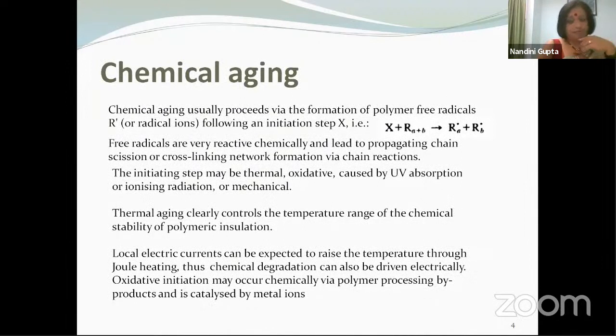Sometimes it can lead to a good thing. For example, if you prepare an epoxy resin sample, before we perform any experiments we just leave it in the laboratory at room temperature in a dry condition. Just that 21 days of aging leads to cross-link formations. The cross-linking is complete, which is what we want. But that may be what we want, but over time we will have situations that we do not want. We will have chemical changes that we do not want. So chemical reactions are caused.